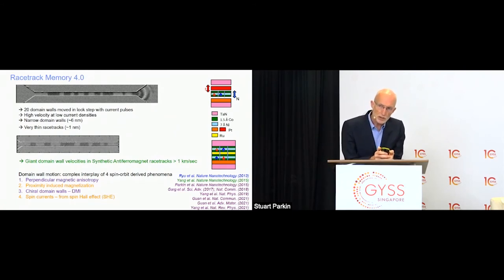But at the bottom, you can see a synthetic antiferromagnetic racetrack where these domain walls are moving at 1 kilometer per second. So we're just showing you a series of images after we've applied ultra-short current pulses. And so basically, this is a very interesting racetrack memory technology where, using synthetic antiferromagnet magnetic racetracks, we can make technologically relevant devices. And we've demonstrated in my laboratory in Germany that we can shrink the width of these racetracks to technologically relevant sizes of the order of 15 nanometers. And it turns out the speed of the domain walls is unchanged for the same intensity of the current pulses.